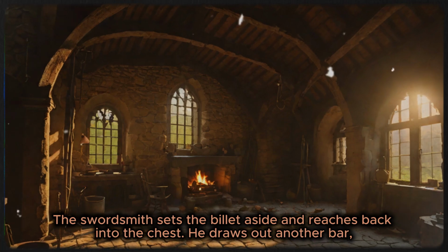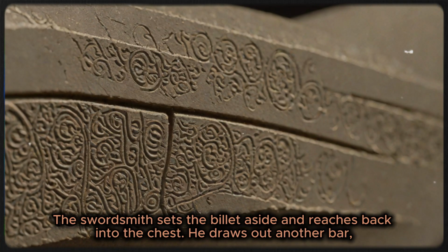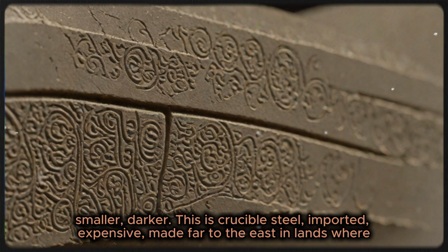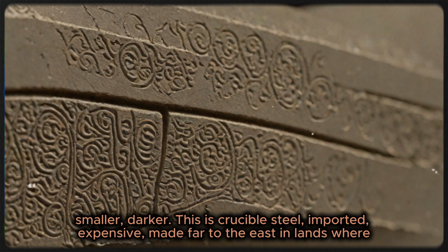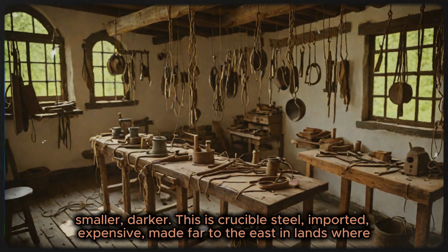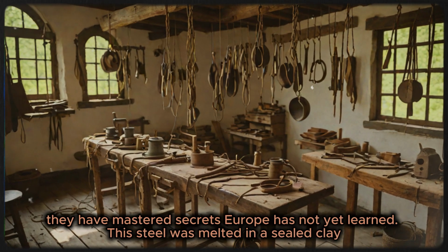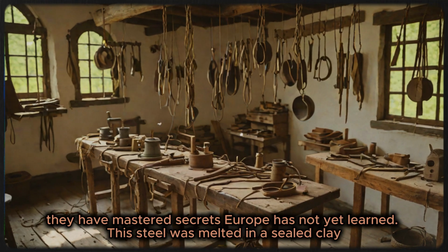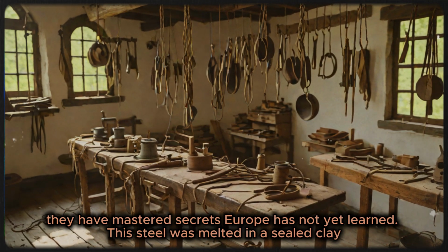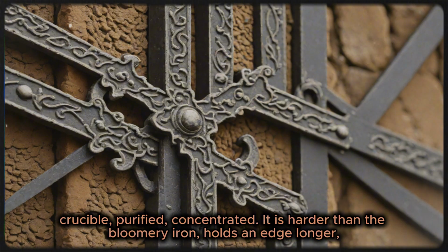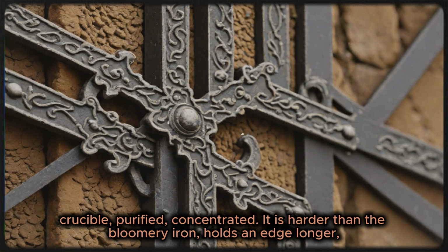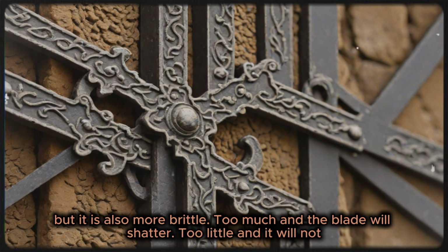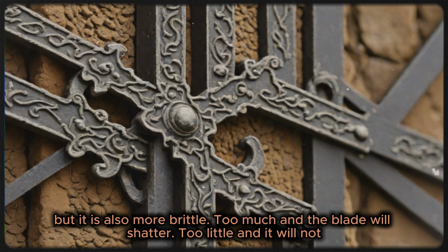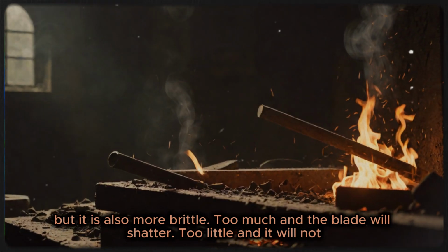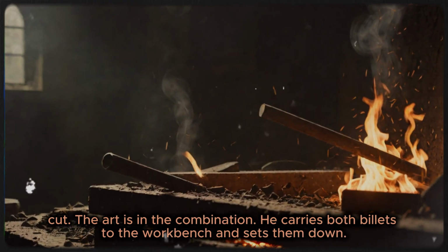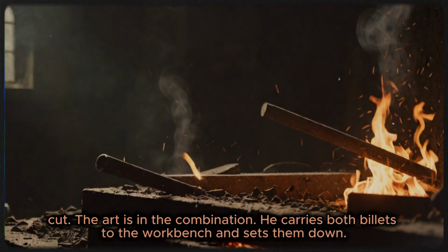The swordsmith sets the billet aside and reaches back into the chest. He draws out another bar, smaller, darker. This is crucible steel, imported, expensive, made far to the east in lands where they have mastered secrets Europe has not yet learned. This steel was melted in a sealed clay crucible, purified, concentrated. It is harder than the bloomery iron, holds an edge longer, but it is also more brittle. Too much and the blade will shatter. Too little and it will not hold a cutting edge. The art is in the combination.